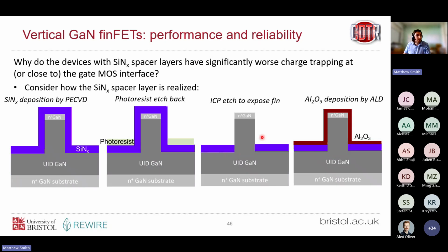Essentially what we have is this problem where we've deposited our silicon nitride, etched it back using a photoresist etch back process, exposed our fin, and then deposited our aluminium oxide. So this fin region here is damaged by this deposition and possibly also the removal process.